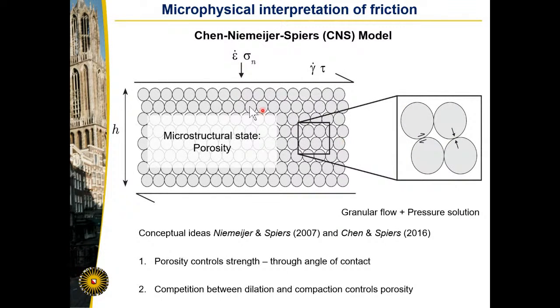Now, we've over the years developed a model which we dubbed the Chen Niemeijer Spiers model, or CNS model, and it's basically centered around the assumption that the porosity of our gouge layer controls strength, and that is through the angle of this contact. As the porosity goes down, the angle goes up, so that means that the strength has to go up.